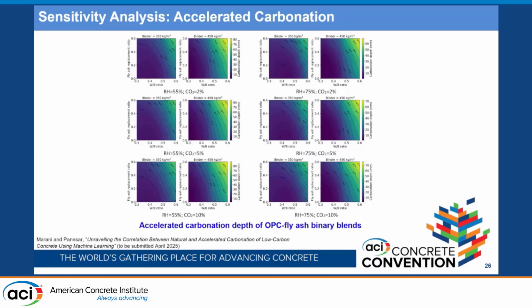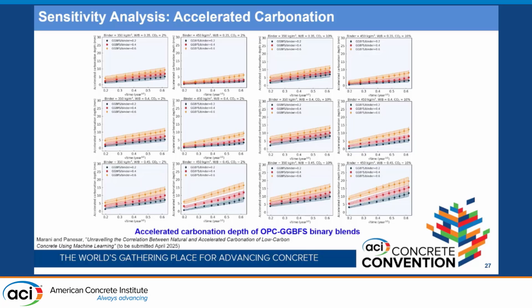So here we have relative humidity, CO2 concentration, fly ash replacement level, and water-to-binder ratio, and you can see that for different values, the model was able to capture those effects and could pretty much reliably and accurately predict the carbonation depths. These are the same results, but for the slag OPC binary blends. Again, the model had a good performance on capturing the effect of different parameters.